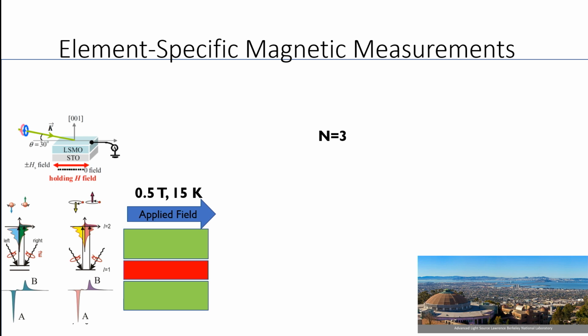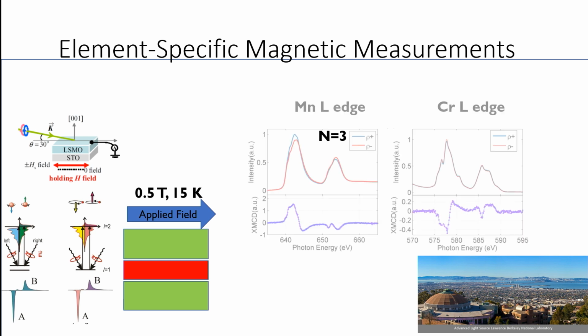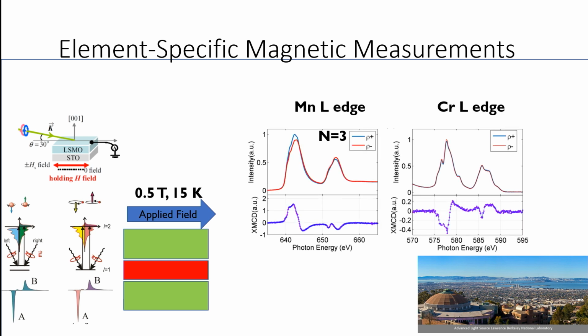We're going to use left and right circularly polarized light incident on that sample and measure the absorption at the manganese edge and the chromium edge, so we can measure the magnetism on the chromium sublattice and the manganese sublattice separately. So in this experiment, you do this experiment twice with the left and right circularly polarized light. You take the difference.